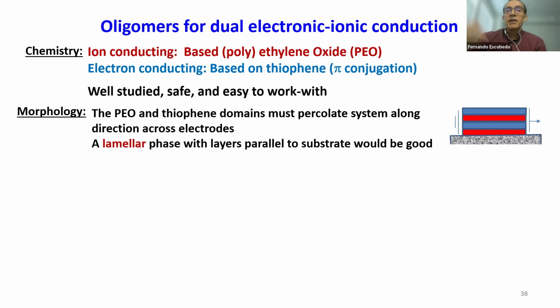And so we thought that a lamellar phase, layers that are parallel to the substrate, would be really good in some ways, because, for example, there are simple techniques that will allow you to functionalize the substrate so that basically one of the blocks or one of the chemistries would like to be down there. And if the system wants to form a lamellar phase, you have this nice registry of the lamellae with layers parallel to the substrate. And then you have this conduction that will go, say, from left to right or vice versa.